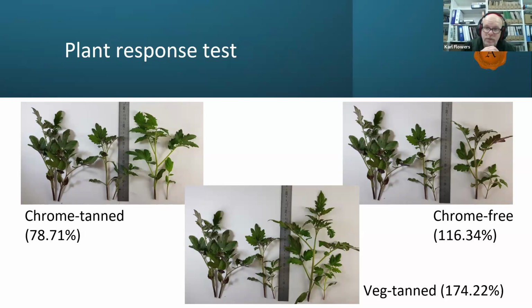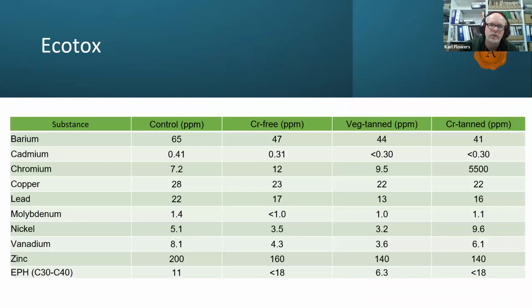Now, the bottom, the vegetable tanned, grew 174% more than the blanks. And that indicates that if you did make a compost out of vegetable tan, it might not biodegrade and disintegrate as well as the other materials would. But if you had to take that compost and place it into agricultural land and grow your tomato plants in it, you could be expecting a bioenhancement of that plant to the magnitude that we see here, 174% more than the plants grown in normal blank with no material in it.